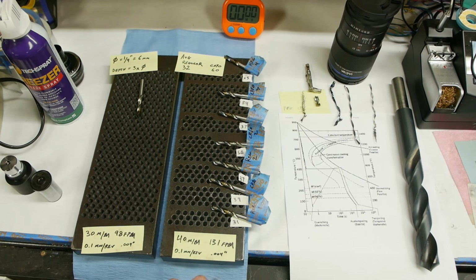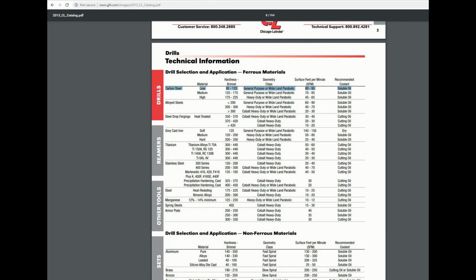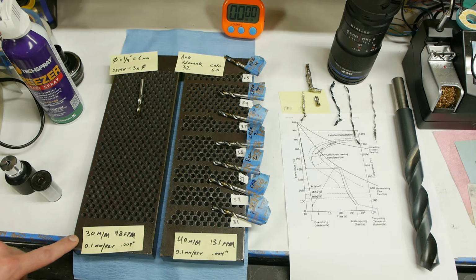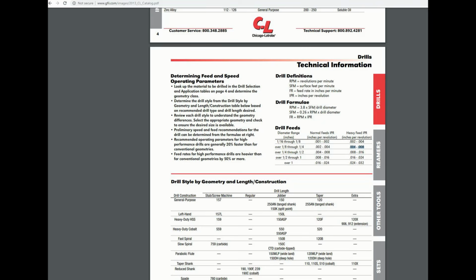I should add that this is a pretty intense machining setup. So we're running at 131 feet per minute, which is like 40 meters per minute. And we're drilling into mild steel. And I mentioned the diameter is about 1/4 inch or 6 millimeters, and the depth of the hole is 3 diameters. But initially, I started off with this setup, 30 meters per minute being the only change, 0.1 millimeters per rev, or 0.004 of an inch per rev.